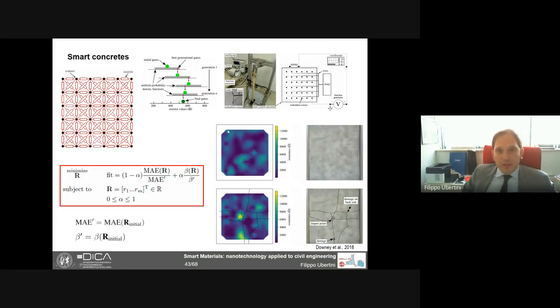To convince you once more, I can show you this other example, the example on the plate. You saw it before. We tried to fit the resistor mesh also for this plate, and then we produced a map of resistive values, the map of the values of the resistor constants. And you see on the right of the slide the results for the intact plate. Of course, you do not see a uniform resistance on the plate because we do not have a uniform material at the end. Then we have the damaged plate, where we apply the calibration procedure, the optimization procedure.